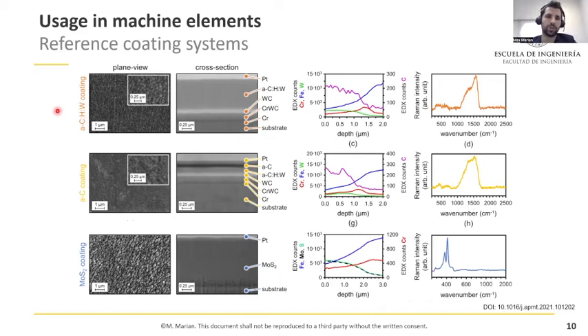Basically, it was one coating consisting of tungsten-doped hydrogenated amorphous carbon, one undoped DLC coating, from the D and G bands from the Raman spectra on the right. We can see that the pure DLC coating has a more graphite-like structure. And finally, we also used an MoS2 coating as a reference with the pretty classical surface properties and structures.